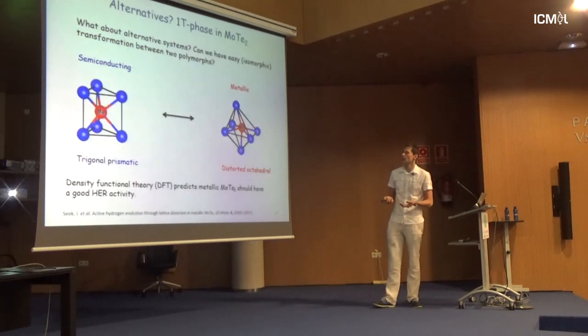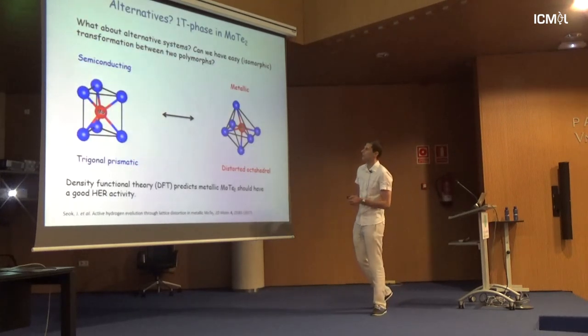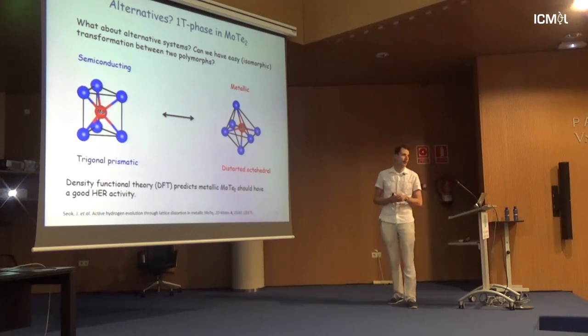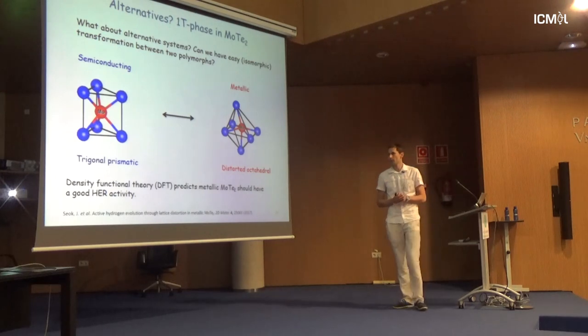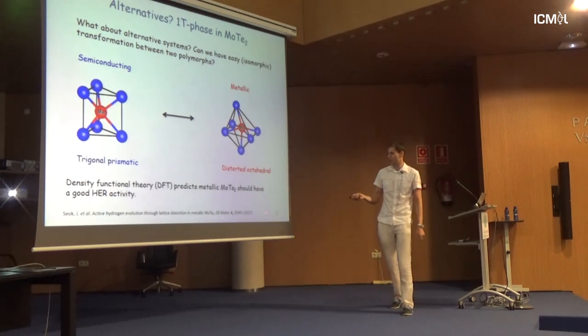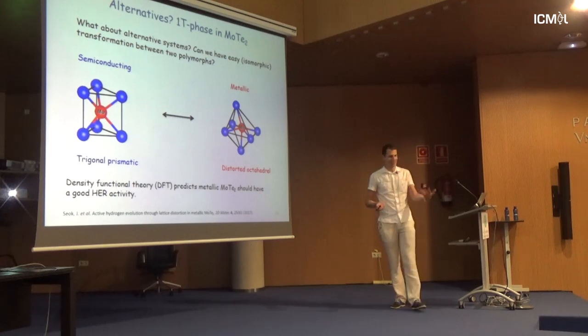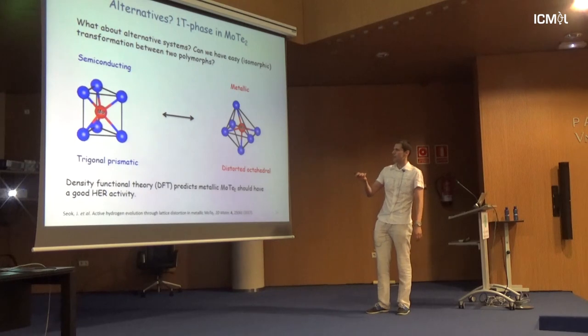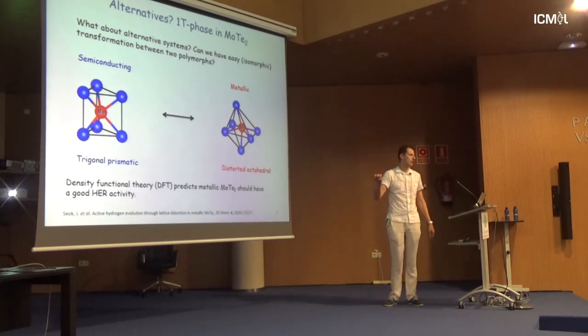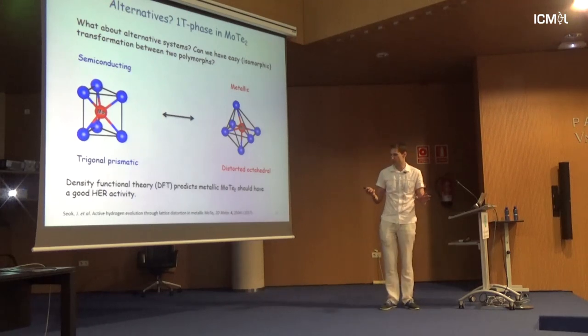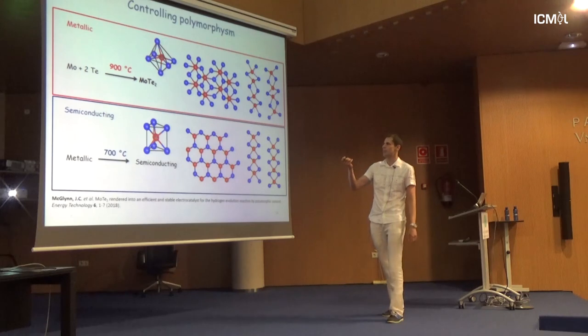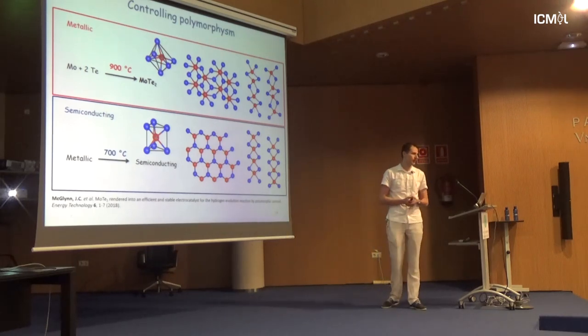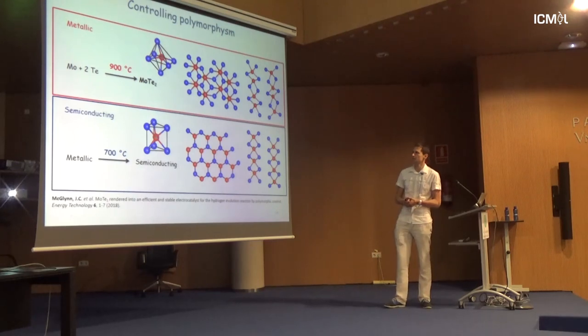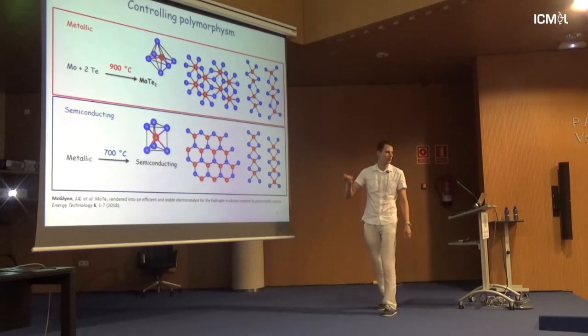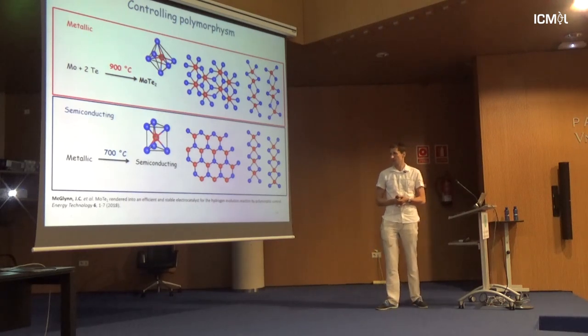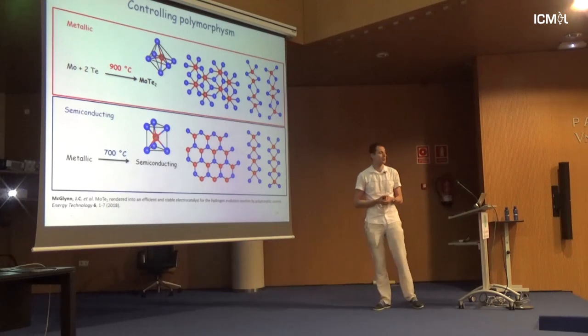So what we tried to do is look into alternatives, and the alternative we found is molybdenum telluride. What is great about molybdenum telluride, and especially DFT already predicted it should be a great electrocatalyst, is that we can play with these two structures without any need for chemical intervention. So all you need is a furnace to make a metallic phase. We made it at 900 degrees in a sealed ampoule directly from the elements. It's kind of distorted octahedra as base units of the structure.